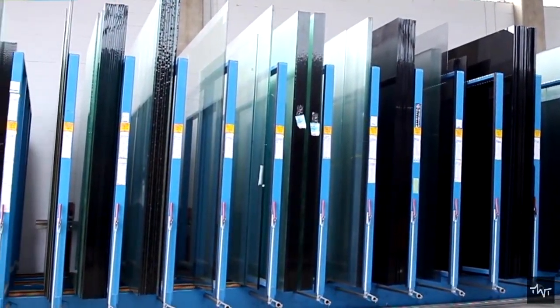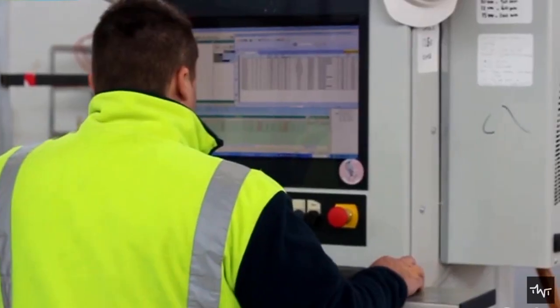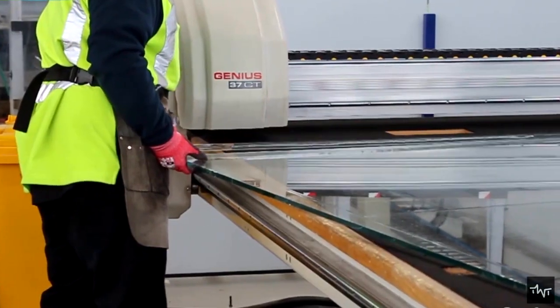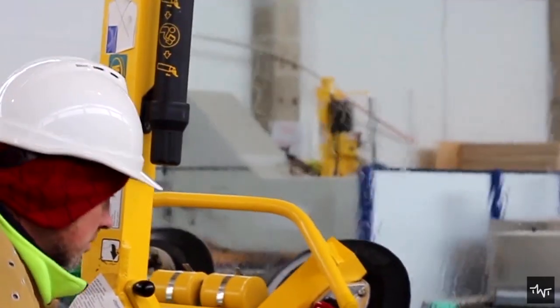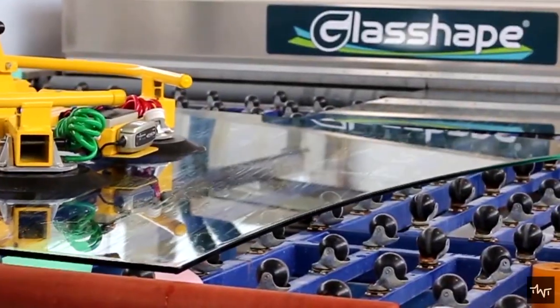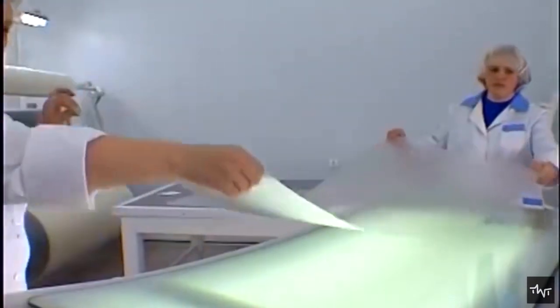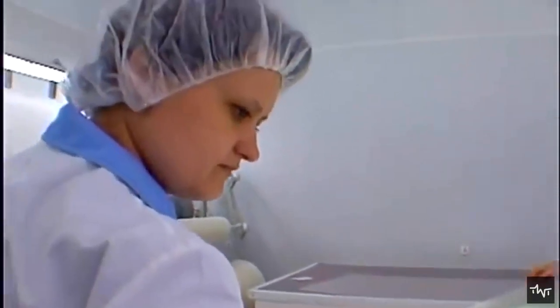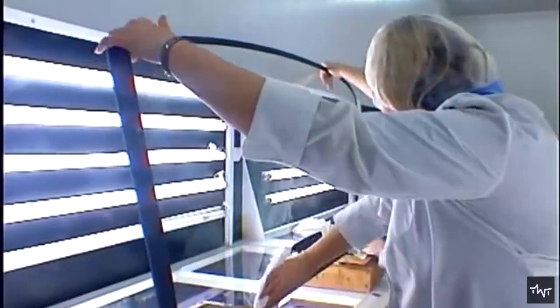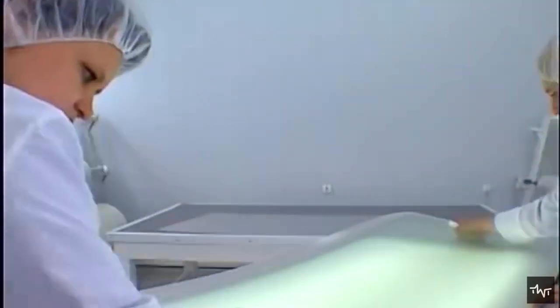Traditional bulletproof glass is made from alternating layers of 3 to 10 mm thin glass and plastic, where the plastic is simply a thin film of polyvinyl butyral around 1 to 3 mm thick. Newer, stronger kinds of bulletproof glass use a sandwich of glass and plastic made of acrylic glass, ionoplast polymers such as Sentry Glass, ethylene vinyl acetate, or polycarbonate with thick glass and plastic layers.